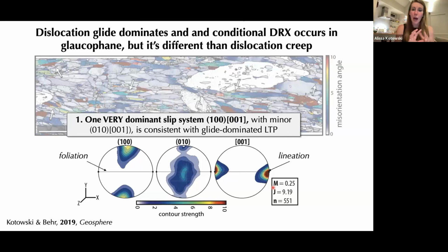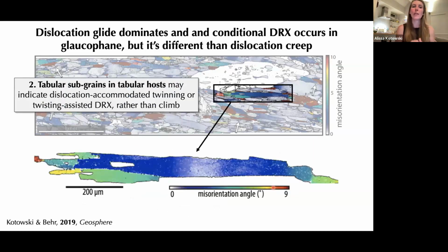This is consistent with glide-dominated low-temperature plasticity in these rocks. And then the second observation is that we have tabular subgrains in tabular hosts. And so I think what this is saying is that the actual recrystallization mechanism making new dynamically crystallized grains might involve some amount of twinning or twisting rather than dislocation climb. And so if this is the case, then this actually looks more like a dynamic recrystallization by plasticity, twinning, and twisting accommodated mechanism rather than conventional or classical dislocation creep.